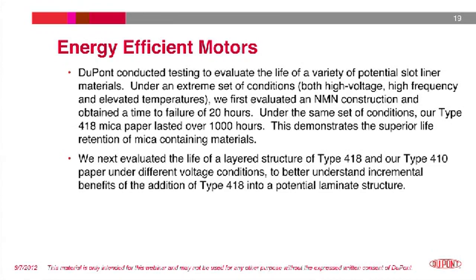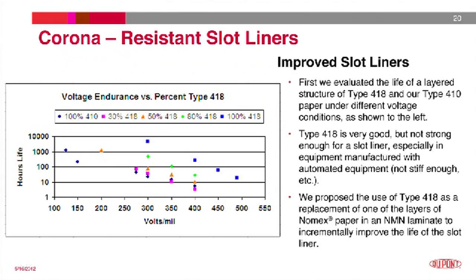The Type 418 paper has much better resistance to partial discharge due to the mica content. However, mica-containing products tend to be quite weak mechanically. We next evaluated the life of a layered structure of Type 418 and our Type 410 paper under different voltage conditions to better understand incremental benefits of the addition of Type 418 into a potential laminate structure. This chart shows the results of the testing of layers of Type 410 and Type 418.